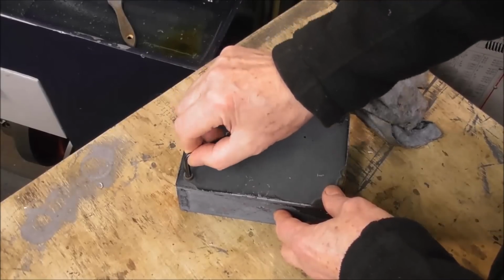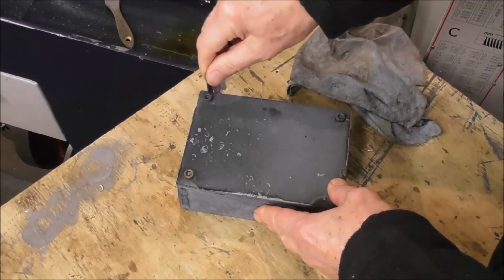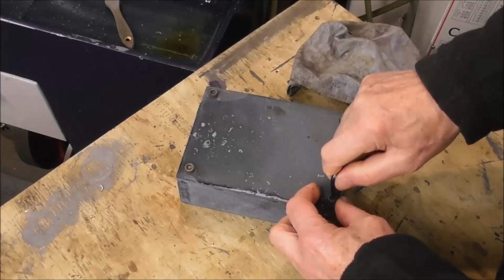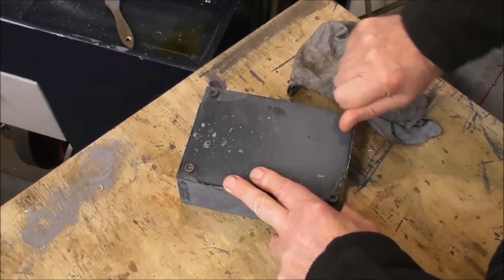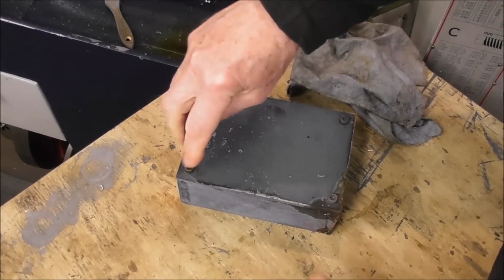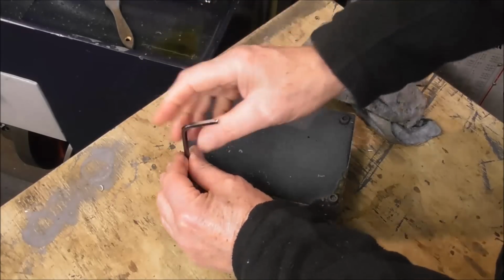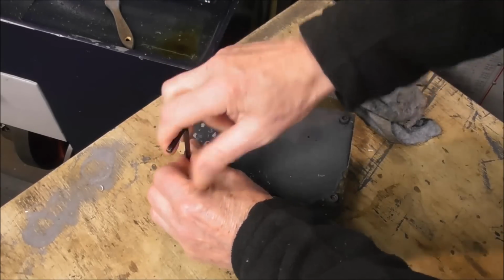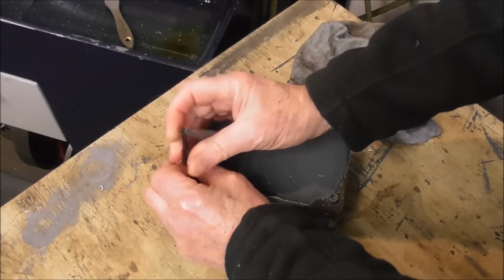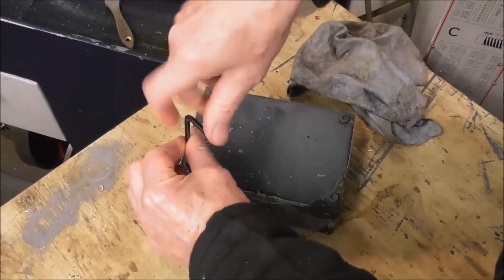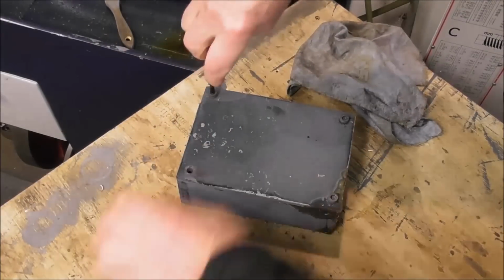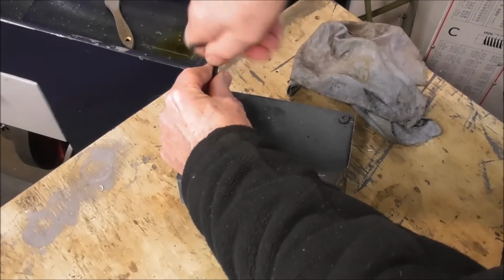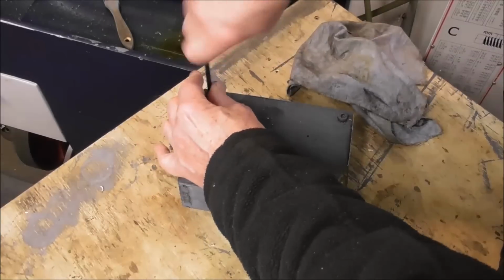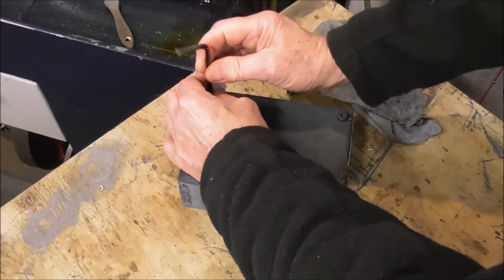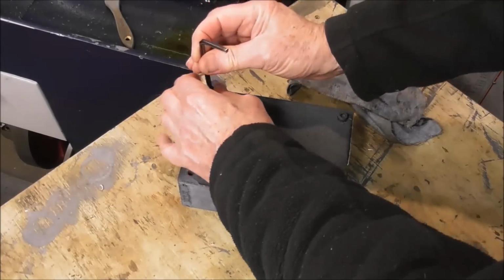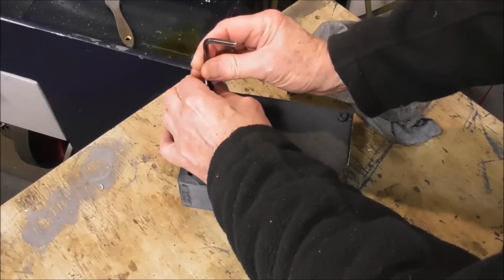Alright, well, let's have a look at it. So that was coming up to temperature to 880 degrees C. Probably took about an hour and a half to reach temperature, and you can see the temperature has done a lot less damage at that lower temperature. Although I have used stainless steel screws, so that they've resisted oxidization pretty well. But the box itself looks like it hasn't got that big layer of oxidization around the outside. I guess once you get up above 900 degrees, things start changing rapidly.